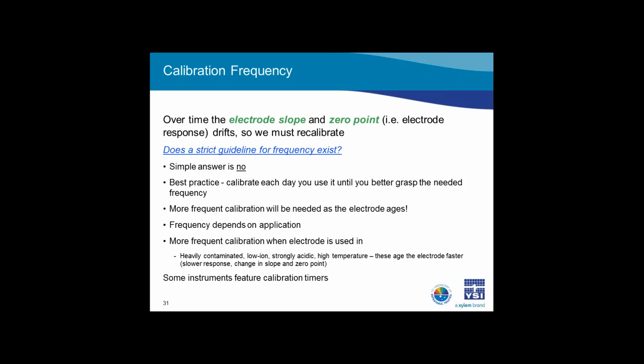I suggest, as a best practice, start by calibrating the system every day you use it. If you find, for example, that you are using the system every day and the sensor is holding its calibration adequately for 2 or 3 days, then you yourself may decide to only calibrate every 3 days. Another example would be if you're only using the instrument once per week. In that case, I would definitely perform a calibration before each use.